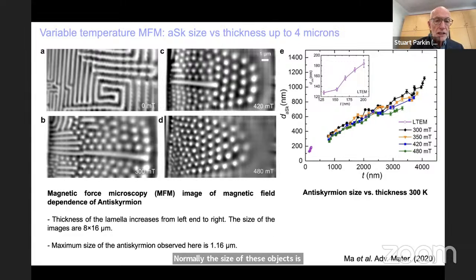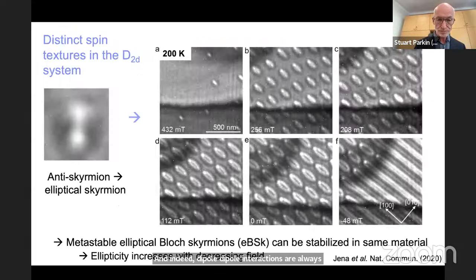Normally, the size of these objects is determined by the ratio of the DMI to the Heisenberg exchange. So in this case, it turns out that the dipole field suppresses the size by nearly an order of magnitude. So the dipole interactions play a very important role in this particular case. And indeed, dipole interactions are always important in magnetic nanostructures on the nanoscopic scale.